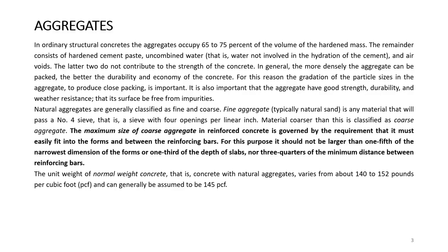There is another requirement for the size of coarse aggregate: it should pass through the gap between reinforcing steels. In beams especially, the reinforcing steels are very close, so the aggregate size should be properly chosen — the aggregate size should be three-fourths of the gap between the bars.